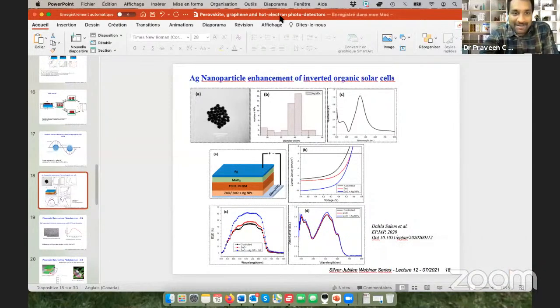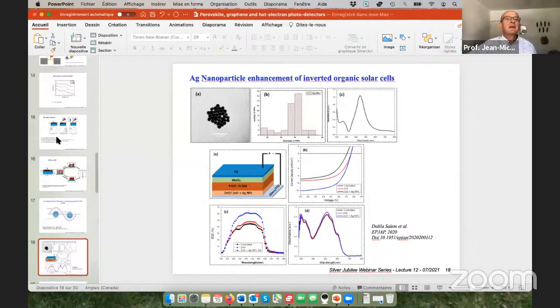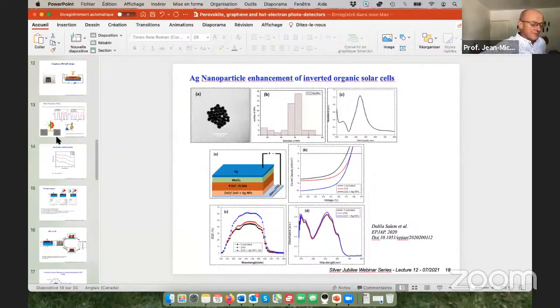Praveen, do you have any questions? You are muted. Yes, actually, I wanted to ask, what was the maximum shift that you could achieve in the graphene Fermi level? The maximum shift? Yes. Not a lot. We tried to experiment with an infrared laser at 10 microns, which is about 100 milli-electron volts. So we had a sensitivity to the infrared laser at 10 microns. So I assume we can shift typically 100 milli-electron volts. I don't have the exact number.